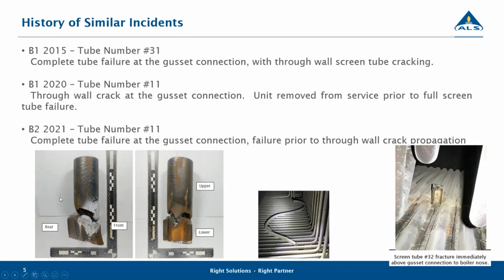If you look at the failure, just what it looks like, you can see here's the two brackets coming up from below the nose, and it basically completely ruptured the top tube. So that was completely separated. So there was no leak. It was just a complete failure. And there you can see the screen tube lying there in the boiler. And there is the stub that's remaining. So that's the little piece that comes through the nose. And there are those two brackets. So it just literally broke off above those two brackets.